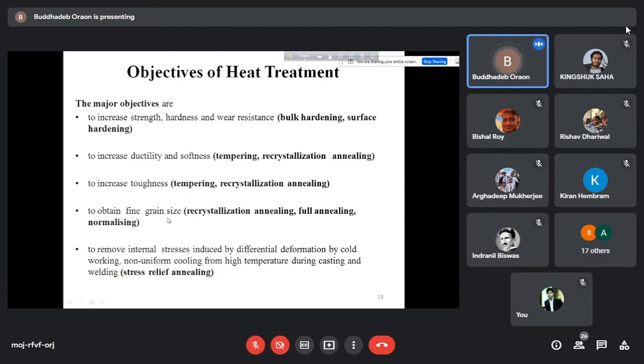When you want to get a fine grain size, that means you are going to increase the strength. If the grain size becomes finer, then obviously from the Hall-Petch equation, as you know, the yield strength will increase. Then, to remove the internal stresses induced by differential deformation. Differential deformation means whether you are performing cold working, hot working and all that. Then non-uniform cooling. When the cooling rate is not uniform, we have seen that there will be segregation and coring. That makes the material inferior so far as property is concerned.